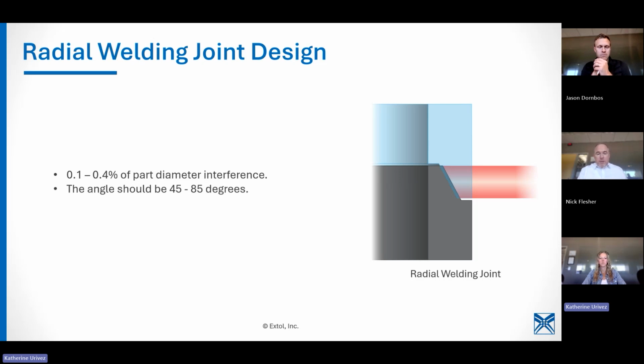We've helped customers design a taper joint, 45 to 85 degrees. We like 45 degrees if you can get away with it. And then your part interference. This is probably the trickiest thing with this weld joint in a radial joint. You need the interference, and you're going to have to hold it relatively tight. So just keep in mind, if you've got a round part, we're more than happy to help you with that as well.